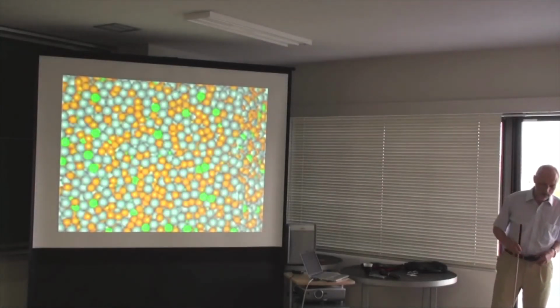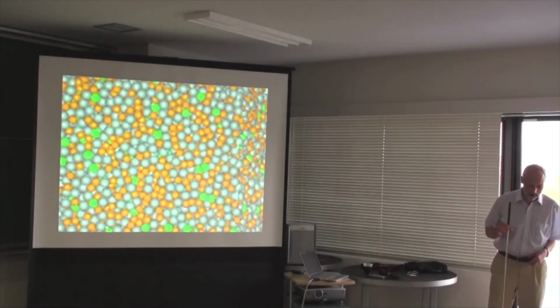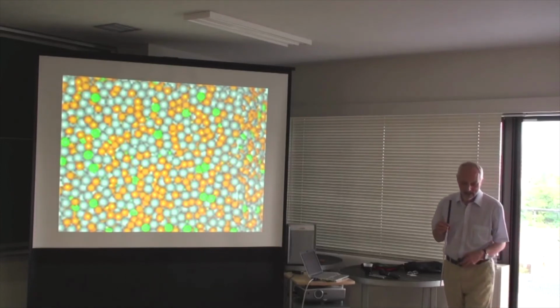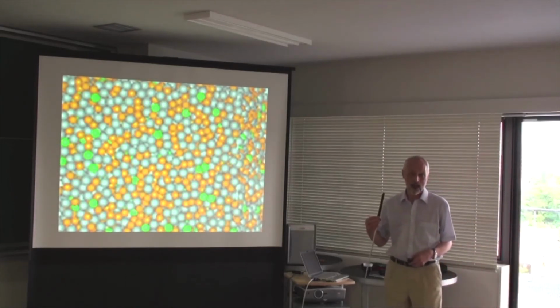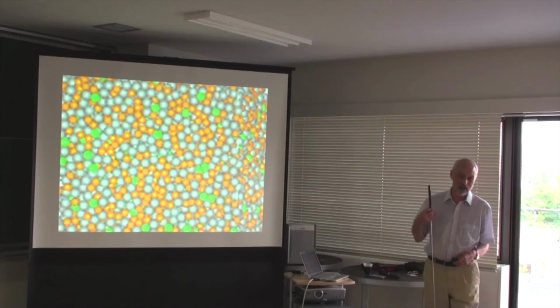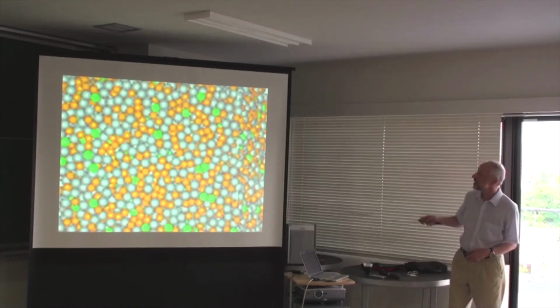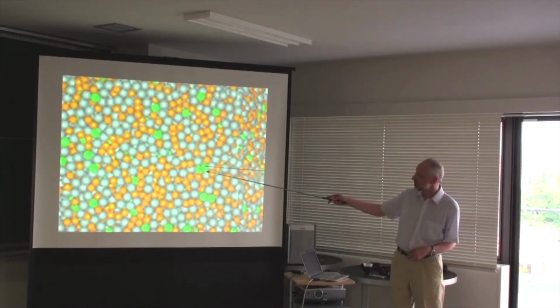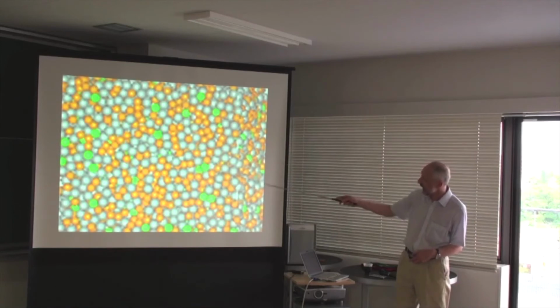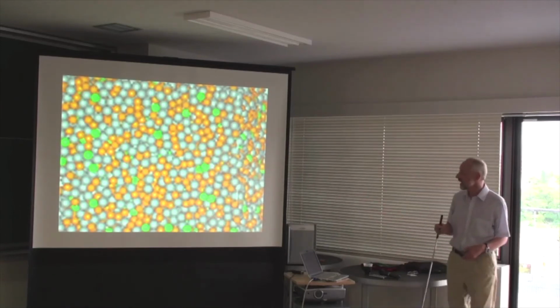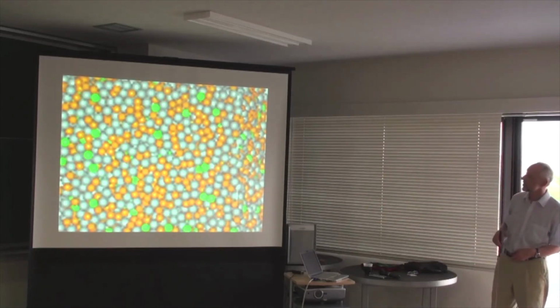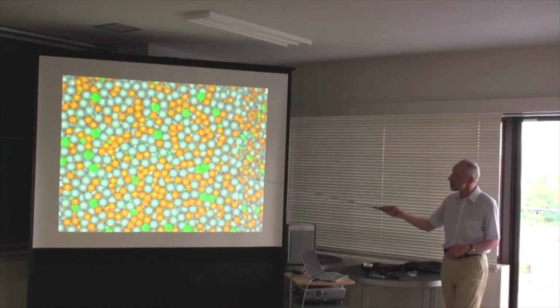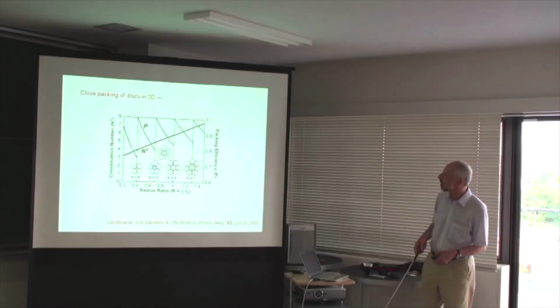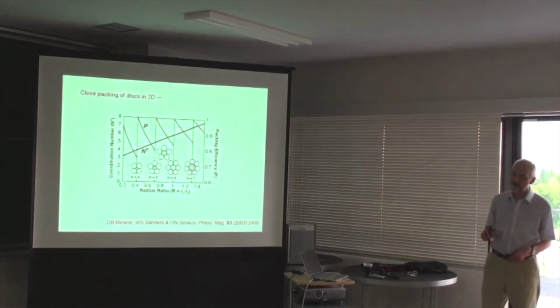I think one of the most intriguing things about glasses is that it's easy to say they are disordered, and they seem to be disordered relative to the crystal. This is a simulation of a copper, zirconium, aluminium mixture, atoms of different sizes. Glassy structure certainly looks disordered. But is it really disordered? Well, it turns out not very.